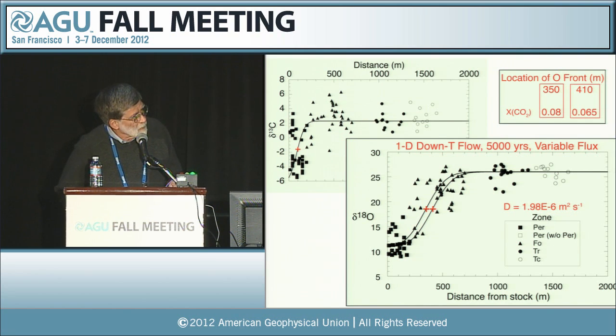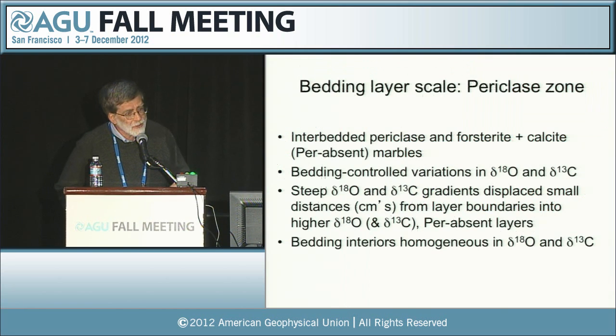Okay, so this is what goes on here at the large scale. We get significant dispersion of the features that we see. At the bedding layer scale inside the Periclase zone, we have interbedded Periclase and forsterite-calcite marbles here, and we see very large bedding-controlled variations in the oxygen and carbon isotopic compositions. We'll see that here in a moment.